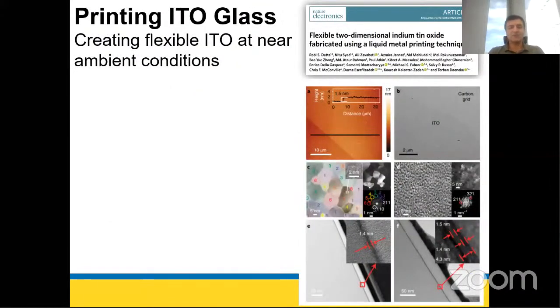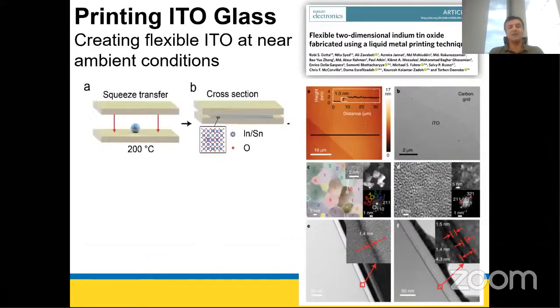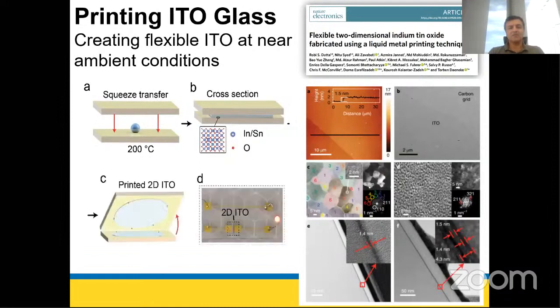Another one, which is going towards commercialization, is making ITO glass. If you look at mobile phones or the display of your laptop or monitor, many of them have transparent conductive material as electrodes because we want to see through. It's made of indium tin oxide, but indium and tin are post-transition metals. Now, how do we do it as a melting process? You can melt them together at 200 degrees, because when you mix them, the melting point goes down. Here we use squeeze printing. That means we squeeze the melt between two substrates, and it's quite transparent. Liquid melt goes out. Two-dimensional materials remain on each side.